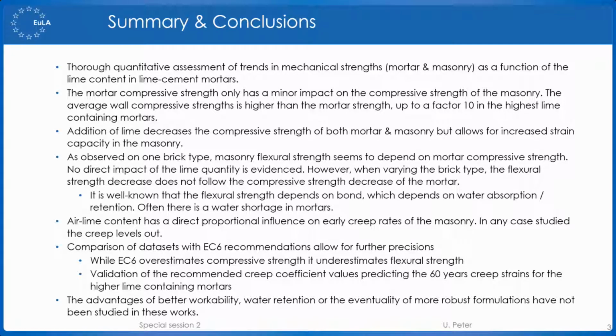of the mortar. And it has been stated also in session 1, just mentioned by Paulo, that it is known that bond depends on other factors, such as water absorption or water retention of the mortar. And it has been stated that very often we observe a water shortage in a mortar, which for sure was not given here in these works, which were undertaken in ideal conditions. It was shown that the lime content has a direct proportional influence on the early creep rates of the masonry, and in any case studied, the creep leveled out as a function of time.